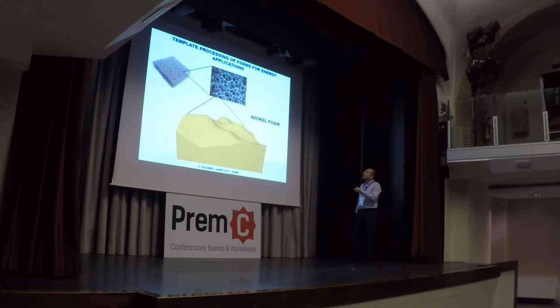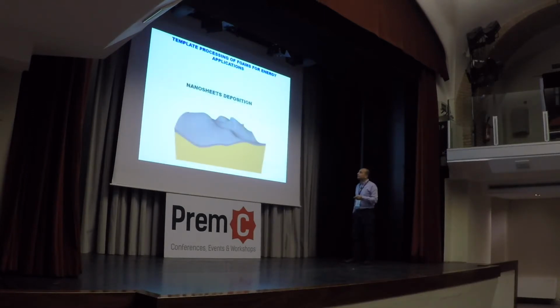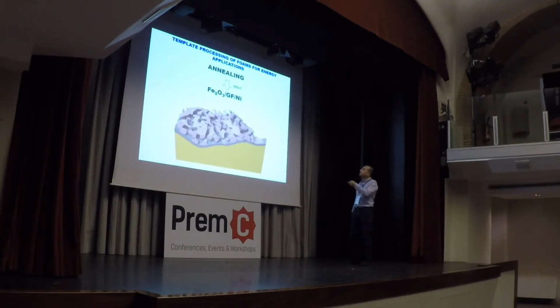You take a template, in this case it's a nickel foam, it's pretty cheap, and you can, from solution, deposit graphene oxide on top of it. So this is still insulating because it's oxidized. Then you deposit iron hydroxide, a precursor, on top of it. Then you treat at high temperature, and at the same time you render these sheets from graphene oxide to highly conductive reduced graphene oxide. At the same time, you transform the precursor into highly porous iron oxide. So you kill two birds with one stone.